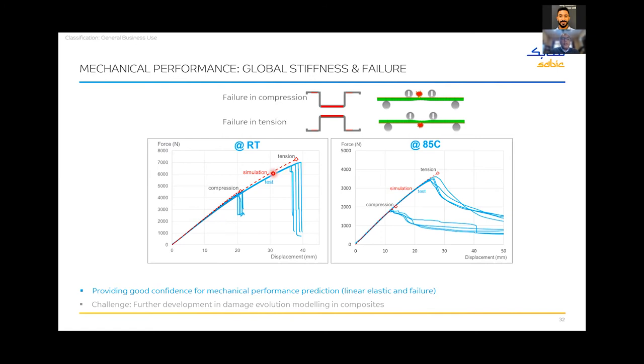And you can see in red, the actual CAE simulations doing a pretty good job, both in terms of linear elastic stiffness, but also being able to predict the onset of failure, the point of failure. Pretty well within satisfaction for this complex hybrid part. We flipped the beam around and did the test in 4-point compression. And we did the same thing. Here's all the experimental data nicely bunched up in compressive failure. And once again, not only stiffness, but also the onset of strength or failure, we can predict quite well through CAE. So quite satisfied at room temperature.